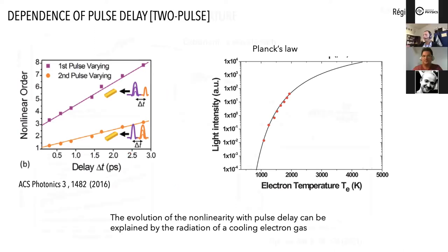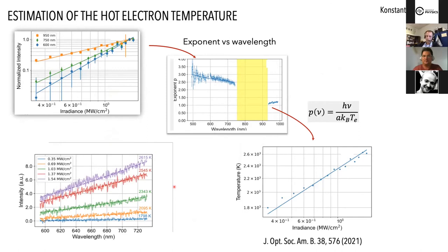Okay, so, estimation of the hot electron temperature. Going to Jonathan's question, how do we do this? We actually have two ways of doing this. We take the spectra for different excitation conditions. And if there is no strong resonance in the structure, we basically have a decaying tail, which is reminiscent of Planck's law, and we just fit this with Planck's law, basically, and deduce the temperature of the corresponding curves.